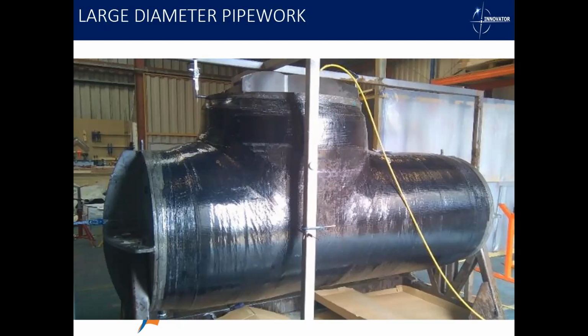But it actually turned out that the spool was designed incorrectly, so there's so much movement in the T-piece itself, hence the vernier gauges that we have there. It was actually moving about 1.5 inches at about 20 bar, so it's flexing so much it was almost breathing, which was quite strange for a test piece. So what you'll see is we've actually wrapped it in carbon fibre. If you've not seen composites before, the carbon fibre is black, whereas the fiberglass is white. And the reason for using the carbon fibre is because it's so much stiffer. It meant we could constrain the movement of the steel and enable it to pass the test.